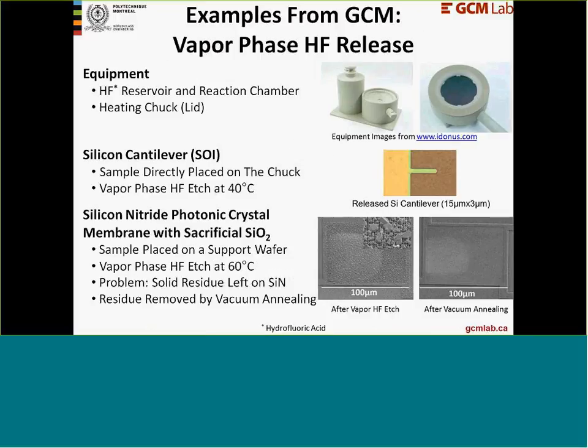I'll give you two examples of surface micromachining using vapor phase HF release. The equipment used is quite simple and consists of three parts: the reservoir, the reaction chamber, and a heating chuck. The sample can be held on the heating chuck by mechanical or electrostatic clamping. The chuck is placed upside down on top of the reaction chamber that is partially filled with HF solution. Example 1 shows a thin silicon cantilever on a SOI chip that's released by vapor HF at 40 degrees centigrade.